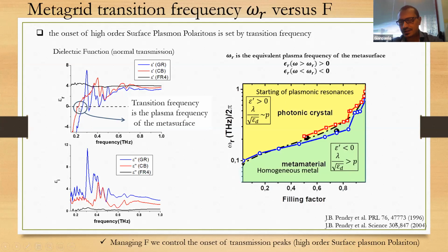So we have studied through simulations the change of this transition frequency, that is basically the plasma frequency of metasurfaces, according to the filling factor. Below this frequency, the behavior of the metasurfaces is completely homogeneous. You don't see any peaks. It's like a mirror. The transmission is almost zero. And no features characterize the spectrum.